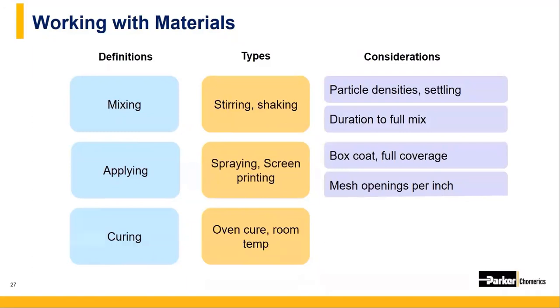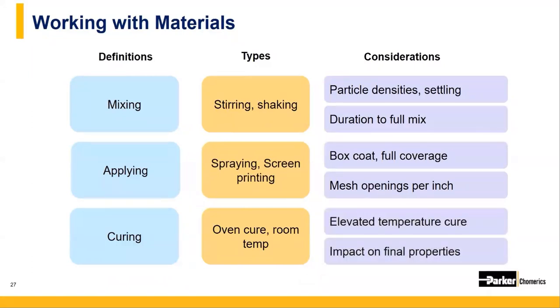All coatings are able to cure in room temperature conditions, but many have elevated cure cycles that can cure the material faster. In most cases, the higher the heat, the faster the cure, but there are obvious upper temperature limits to things like your plastic housing and the material itself. So it's also very important to check the temperature limits on the substrate that are sprayed, especially plastics. Many paints can be cured at temperatures that will damage the plastic substrate and should obviously be avoided. And a very important note, for elevated cure temperatures, the highest recommended cure temperature is usually the one that will give the best mechanical properties.